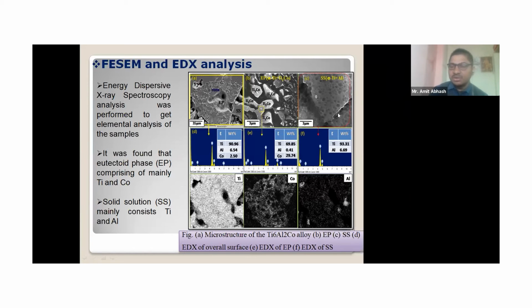And in the solid solution part, we can see only titanium and aluminum. How did we name it solid solution? Again, if you go through the phase diagram, you can find that no phases form in that region. So we are ensured that this is the solid solution part. Also, from the mapping of the first image A, we can see that titanium is distributed in the whole sample. Cobalt is distributed only along the eutectoid phase, where we can see the brighter phase, and aluminum is distributed uniformly.